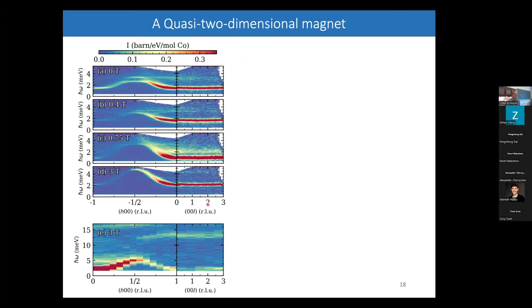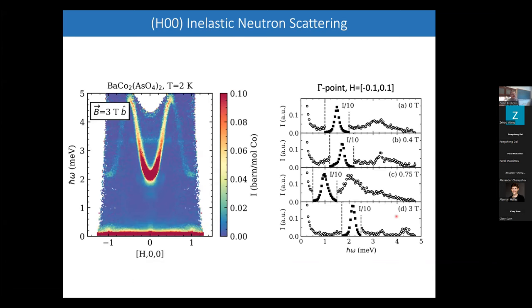I see. What happens then at the gamma point near 5 millielectron volts? What is that, the panel E? This thing? Yeah. I think it might be a continuum, the bottom of the continuum. But he said it's fully polarized. No, it's getting fairly polarized, but if you see here, this one is a spurious component, but this is not. This thing you can see comes and goes with field. And that one actually lies at 4.3 millielectron volts, which is twice this energy. So there still is two-magnon scattering present.